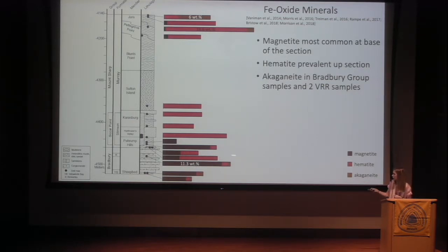We found trace amounts of akaganeite at the base of the section, and then didn't see it again until we got to the top of the Vera Rubin Ridge, where it was quite abundant in one of these samples. And akaganeite is an important indicator mineral because crystalline akaganeite, like we find with CheMin, forms in acidic and saline fluids. We also see evidence for variation in the hematite crystallite size within the section.